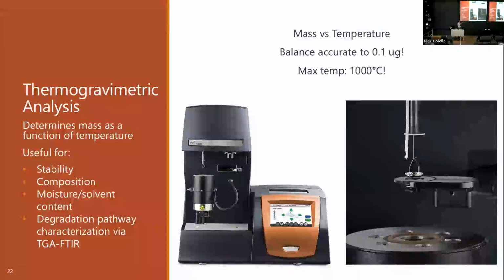The TGA is basically a really nice balance with a really nice oven. So we have very nice control of temperature, and we have very exact control of mass. The balance is accurate to 0.1 micrograms, and the max temperature on the system is 1,000 degrees, and we have very good control up to 1,000 degrees. So we'll heat up a sample and look at how it degrades and how the mass gets lost.